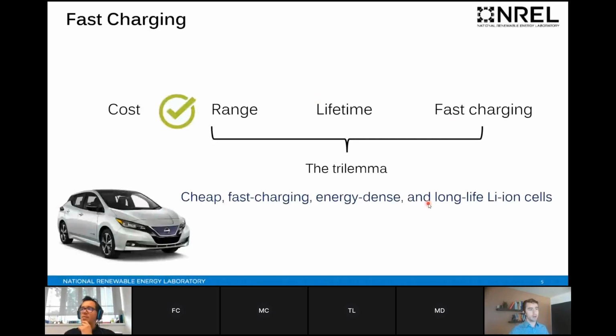Range, lifetime, and fast charging are a trilemma. You can pick 2, but generally the third is sacrificed. And because range and lifetime are the most important, fast charging is the one that has least priority currently. And that's where we are working. So we can achieve high energy density cells for range. They can last for thousands of cycles without significant degradation, but they cannot charge fast. Now, if you do charge them fast, then this will affect lifetime and range, because there's an issue with more rapid degradation associated with fast charging that I'll go into.